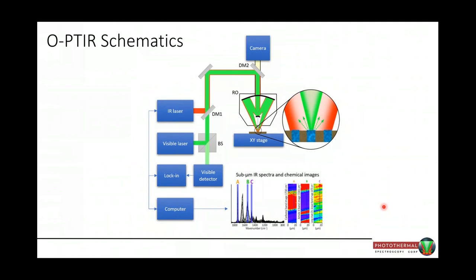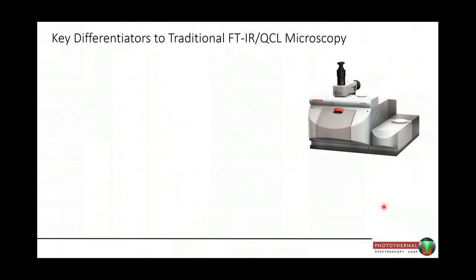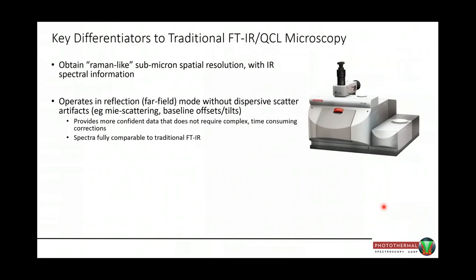So the key differentiators between FTIR and QCL microscopy are that you obtain Raman-like submicron spatial resolution, but you get infrared spectral information. It operates in reflection mode without dispersive scatter artifacts like Mie scattering baseline offsets or tilts. It gets you more confident data that does not require time-consuming corrections, and it's fully compatible, comparable spectra to traditional FTIR.